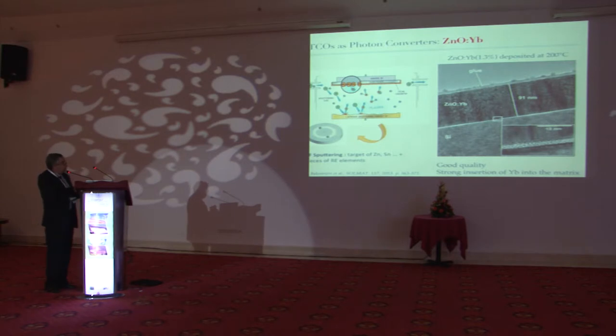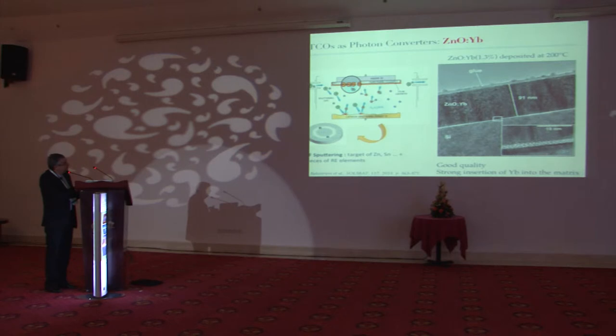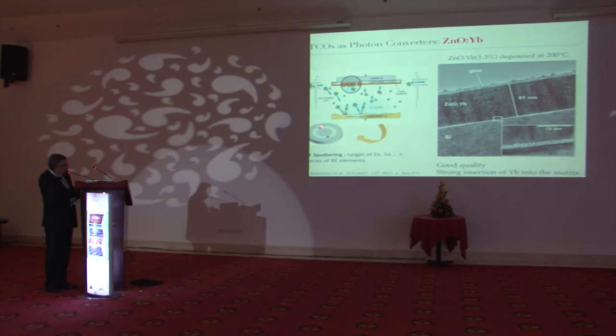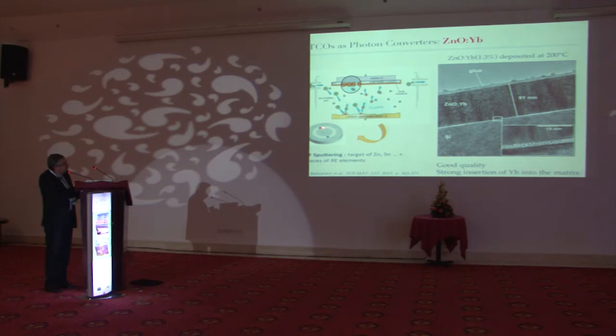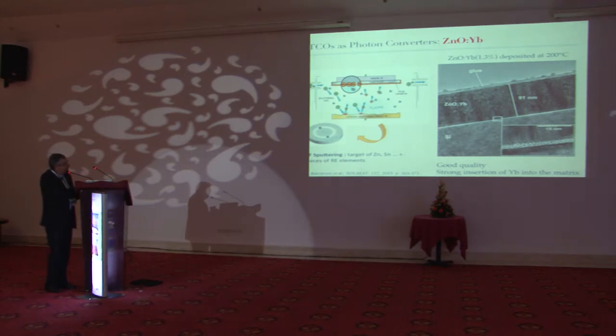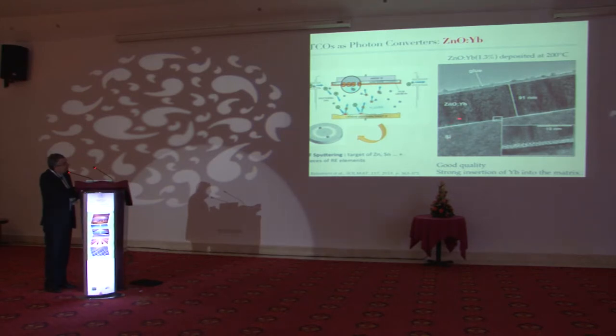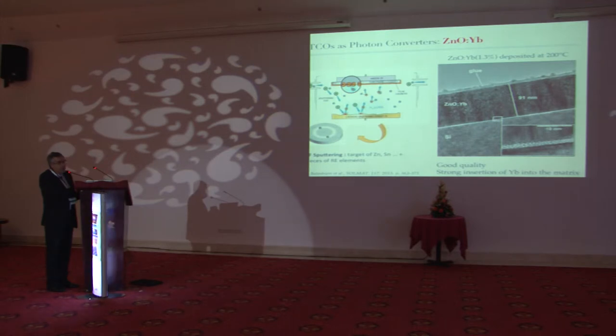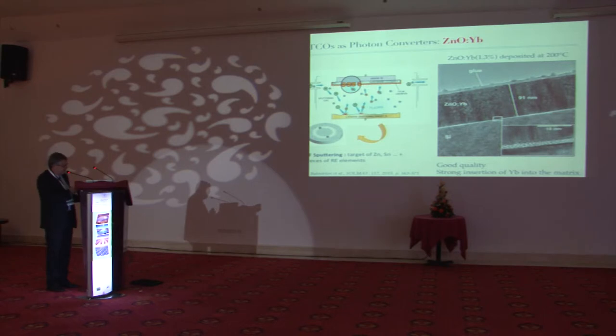On the experimental side, we used a sputtering system where the sputtering target is made of zinc oxide, and we add the rare earth element species in order to have co-deposition under oxygen atmosphere. We achieved very good crystallinity of zinc oxide doped with ytterbium, with a high amount of ytterbium inserted in the zinc oxide — which is exactly what we are looking for.